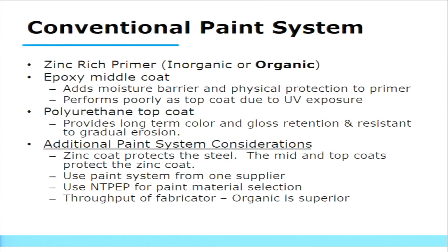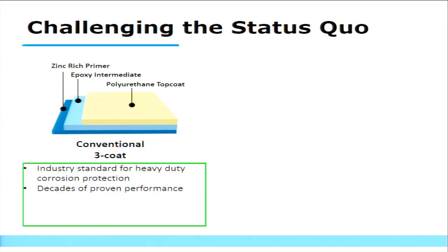An inorganic primer depends on the atmosphere and the moisture content in the air for it to cure. And in some cases can take 24 hours. I believe there's even some states that require it to cure for 3 months. So it really can cause a problem for throughput, whereas organic, that can cure in a matter of hours. So it's definitely advantageous for throughput, and it definitely helps your cost and schedule and efficiency from that perspective.